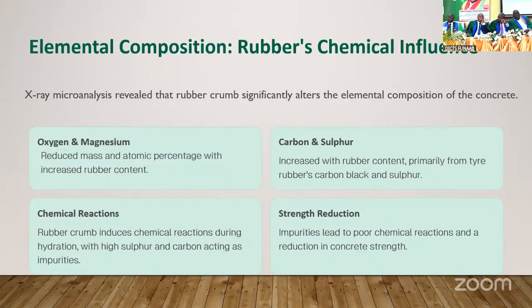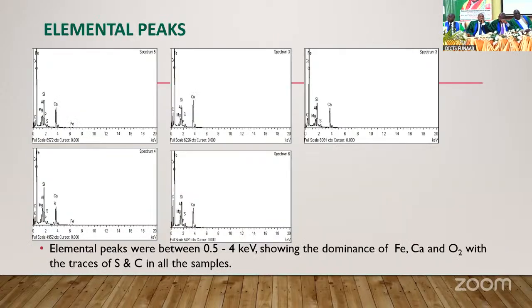Impurities lead to poor chemical reaction and a reduction in strength. We were able to look at the elemental peak. The elemental peaks were between 0.5 and 4 kilo electron volt, showing the dominance of iron, calcium, and oxygen with traces of the impurities, sulfur and carbon, in all the samples.